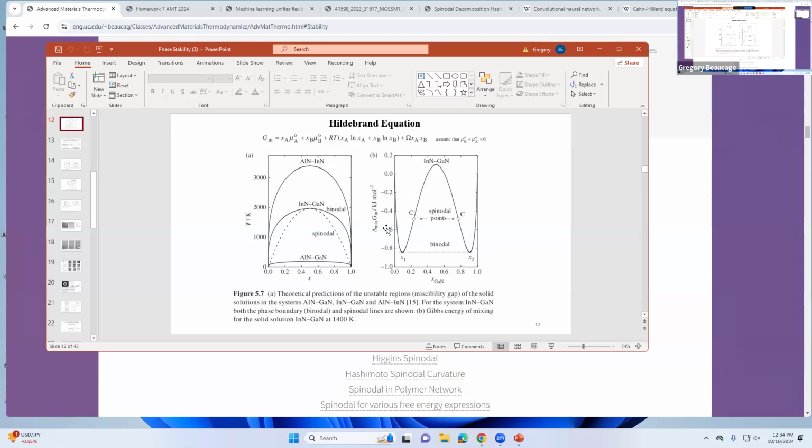So if you get to the immiscible region, if you lower the temperature enough, then this repulsive term dominates and the phases separate. The entropy always favors mixing, this favors demixing. So if you lower the temperature, this drops out, then you get demixing. In that case, this curve goes from being like a smiley face, concave up, to this kind of squiggle thing. So we have the frown face, concave down, that means you're getting separation.